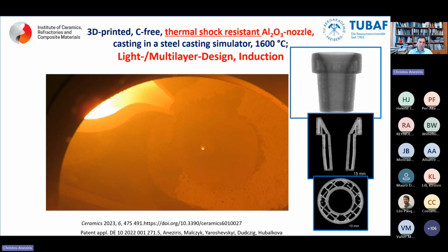We see on the left a crucible which has steel which already melted and a very slight spot in the middle. This is a kind of nozzle, and this nozzle is based on aluminum oxide. Why alumina? I will immediately speak about it. On the one way, aluminum oxide is a low-cost material. On the other way, it presents excellent corrosion resistance against acid as well as basic environments.